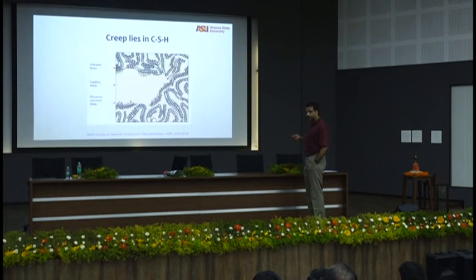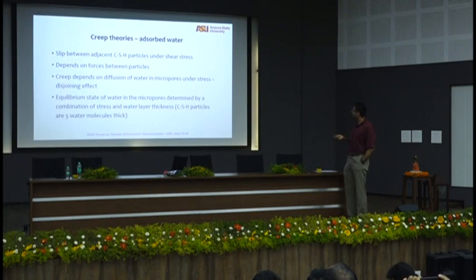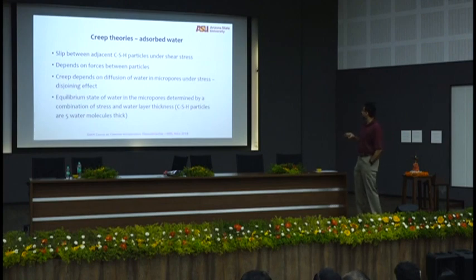Applied stress, and creep lies in CSH. I was telling about this. I'll do some creep theories. Okay, this is the very diluted version of a creep theory. Slip between adjacent CSH particles under shear stress. All of you can relate to that? You have layers of CSH, under load, sliding, slip, easy. Depends on forces between particles, okay.